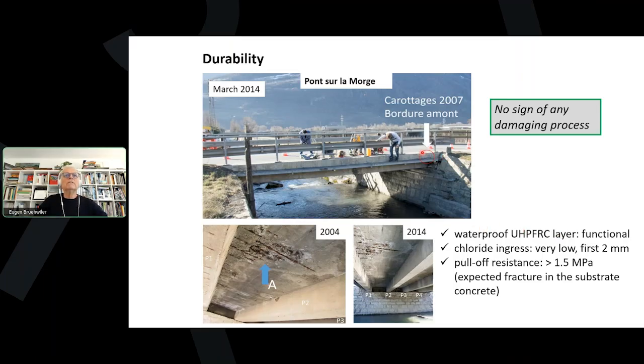Then we also removed here in 2014 and in 2024 specimens, UHPFRC specimens, and we were measuring the chloride ingress, because we have here a road and in wintertime they are spreading de-icing salts on this bridge. And actually we almost didn't find chloride ions in the UHPFRC, only in the very first 2 millimeters depth and very little amount. Then the pull-off resistance was larger than 1.5 megapascal, and the fracture occurred in the substrate concrete, which means that actually the bond between UHPFRC and the concrete substrate is intact.